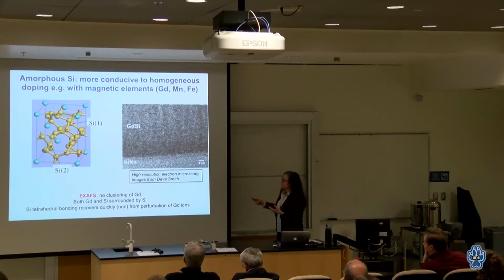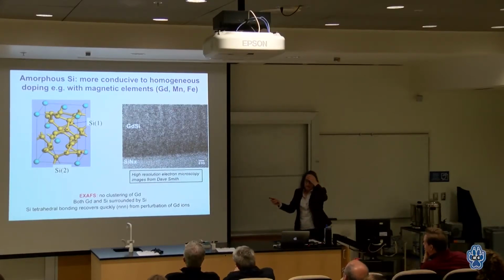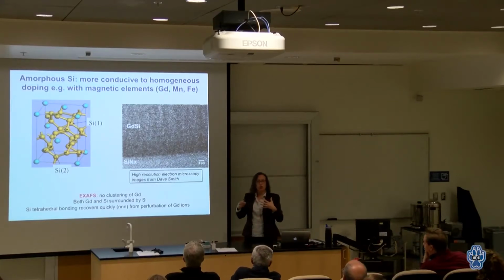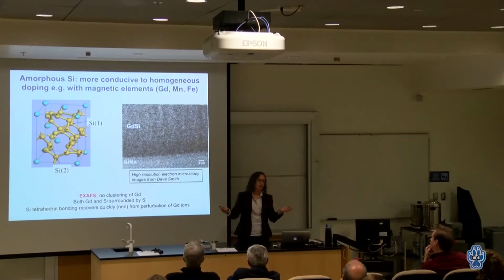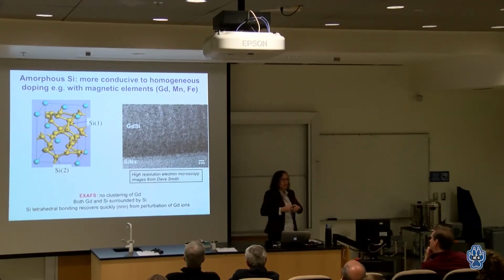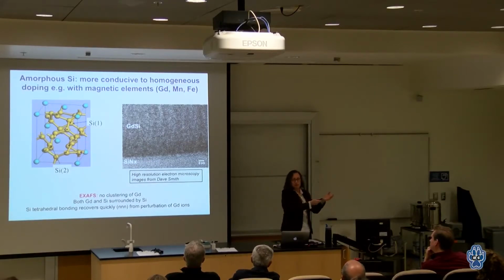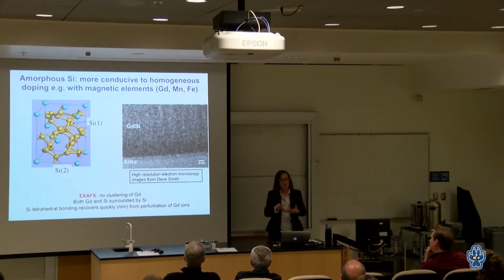So why would I want to do this? Well, I'm a magnetician. There's a whole body of work around taking silicon and doping it. In fact, all of our semiconductor industry is based on doping. A funny thing happens when you start doping silicon: you start off with it being an insulator. You add some element to it, more and more, and eventually it actually becomes a metal. The transition from insulating to metallic is a very fundamental transition. A lot of exotic physics happens at that transition.